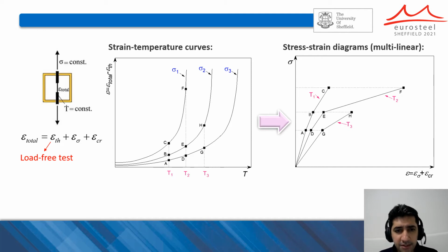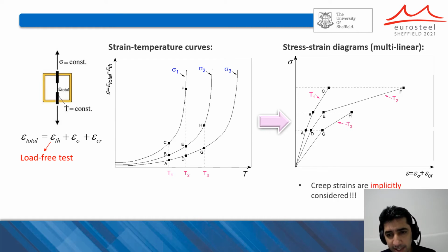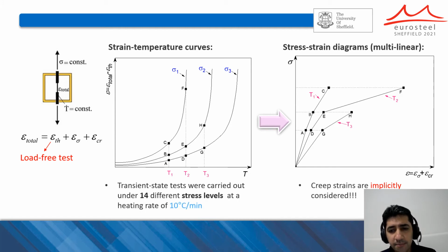The procedure to convert strain temperature curves to stress strain diagrams is shown in the figure. As you can see, at any desired temperature, for example at temperature T2, a vertical line is drawn to cut the strain temperature diagrams, and then the obtained points that are stress strain pairs are plotted and connected together to form a multilinear stress strain curve at that specific temperature level. As you can see in the figures, the good point is that creep strains are implicitly included in these stress strain diagrams. In the present study, transient tests were performed under 14 different stress levels,